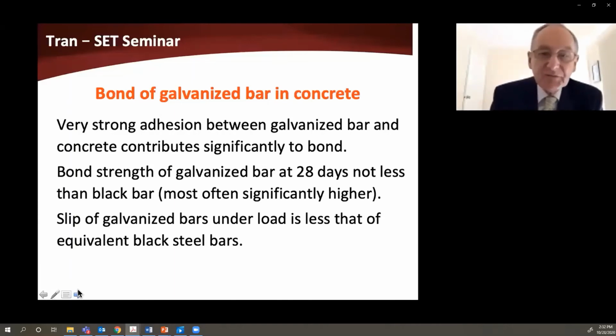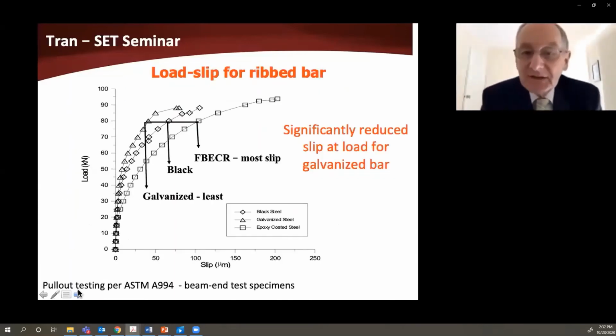And the slip of galvanized bar is also less than that of both black bar and fusion bonded. And here's some data. My colleague and I prepared this data some years ago, back in about the early 2000s. We used ASTM A994 beam end samples to test this. And here's the load slip data for ribbed bar. You can see the fusion bonded shows the greatest slip. There's the black bar as the norm, as the comparison. And here's the slip for galvanized bar.